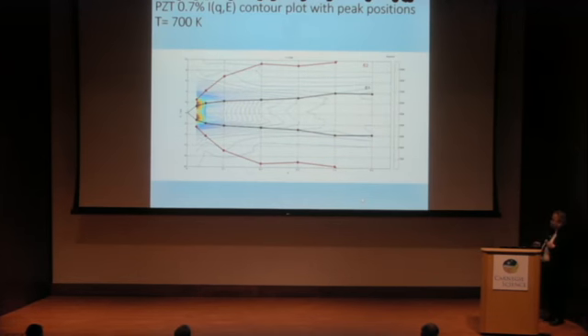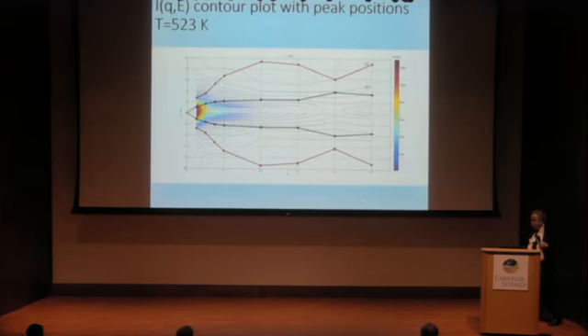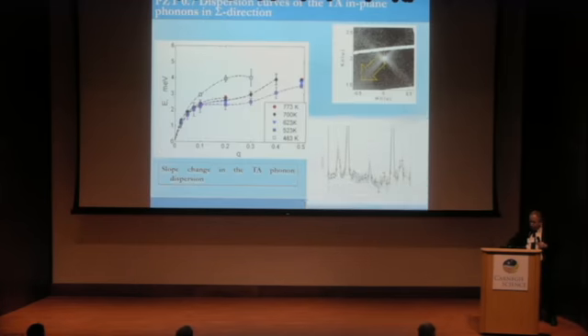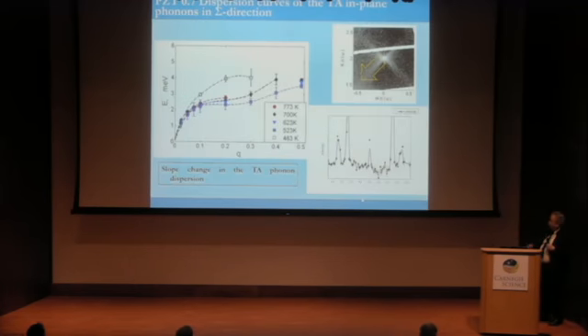But before going to the endpoint, let's have a look at the S(Q, omega) plot, let's say measured with X-ray inelastic scattering. So we clearly do see something soft close to the gamma point. That's far away from the phase transition. As we come closer, here we have now the strong central peak, and we have something close to the endpoint. Now first to this part, to the low Q part.